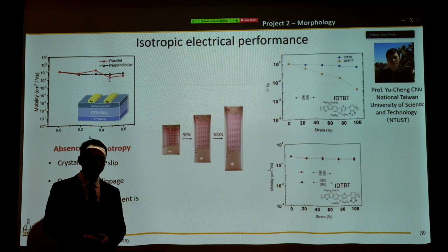And there is no increase in the mobility when the strain direction is parallel to the charge transport direction. That can be explained by the crystallographic slip, as well as the limited degree of alignment in the polymer thin films. And this actually explains another observation from a different publication.